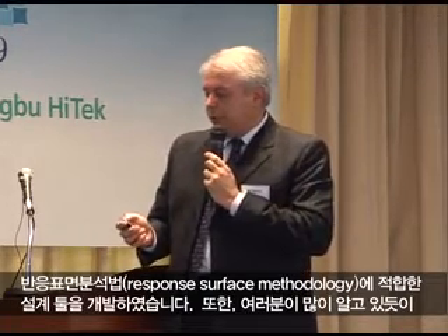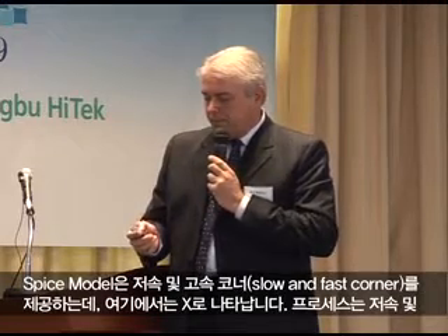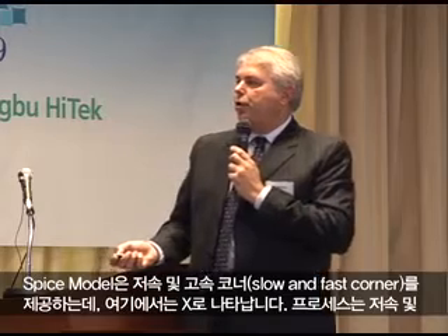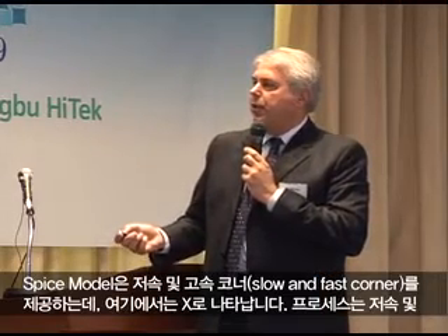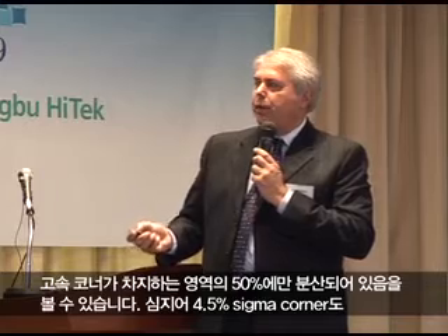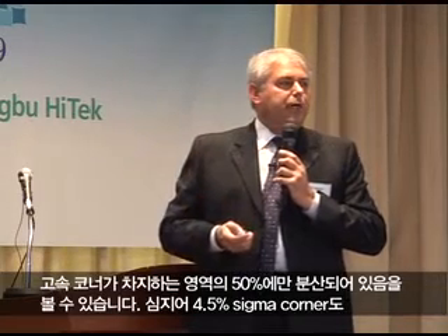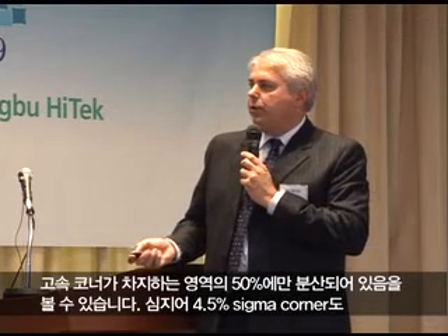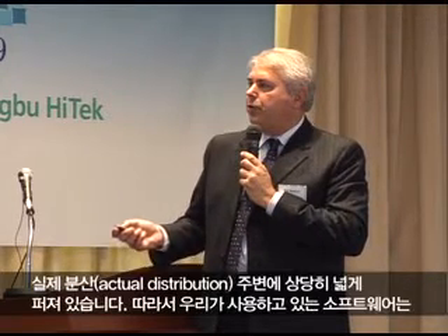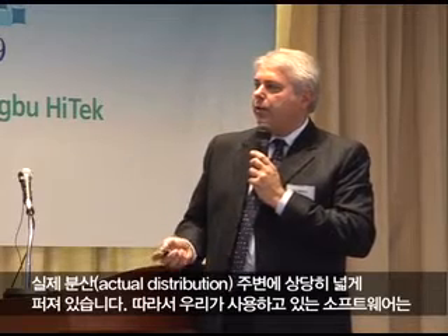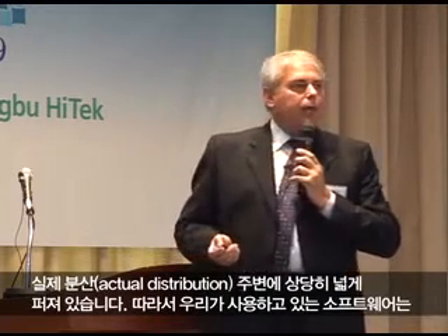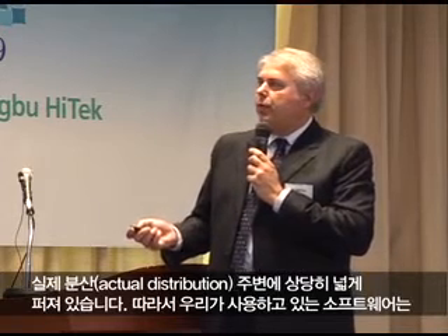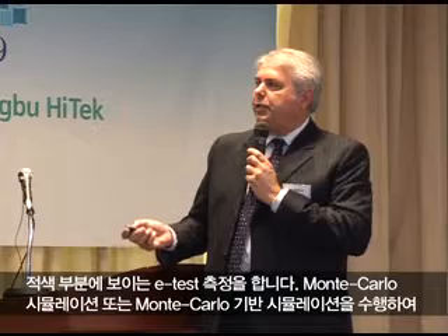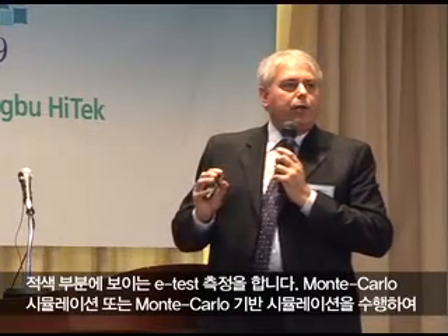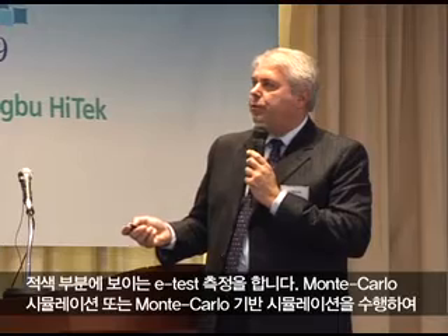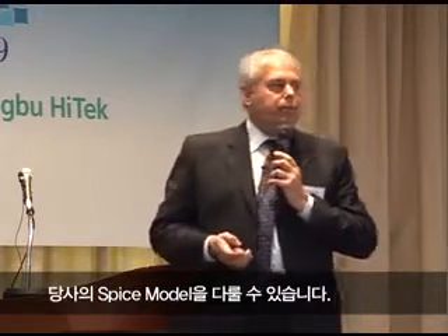In addition, you can see a lot of times the SPICE model will give you a slow and fast corner. Those are shown here with the X. And you can see the distribution of the process is maybe only using about 50% of the area that's covered by the slow and fast corners. And even the 4.5 sigma corners are quite broad around the actual distribution. So software that we're using takes the e-test measurements, which are shown in red, and we can do a Monte Carlo simulation, or Monte Carlo based simulation, to do our SPICE models.